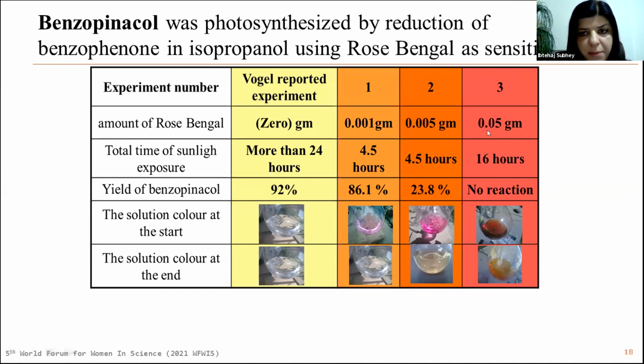So in experiment number 3, when we used 0.05 gram of rose bengal, no reaction happened, no benzopinacol precipitate, because the increase in rose bengal concentration caused a decrease in the yield of benzopinacol. These 2 rows refer to the solution color at the start and the solution color at the end of the reaction.